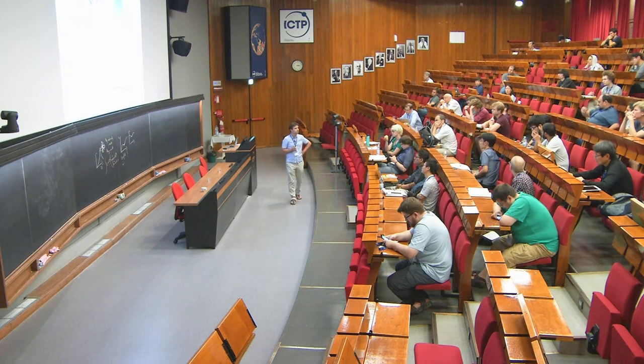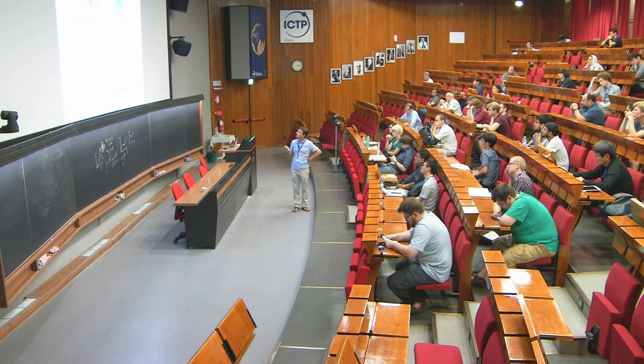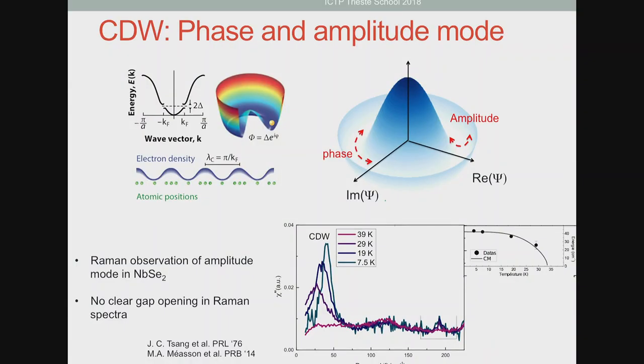Now, we have recent measurements on 2H tantalum diselenide where we actually see the gap. And the gap is at much higher energy. And the gap is very broad. And we see the amplitude mode, it's well inside the gap. So we believe that by comparing with niobium diselenide, this is the amplitude mode.